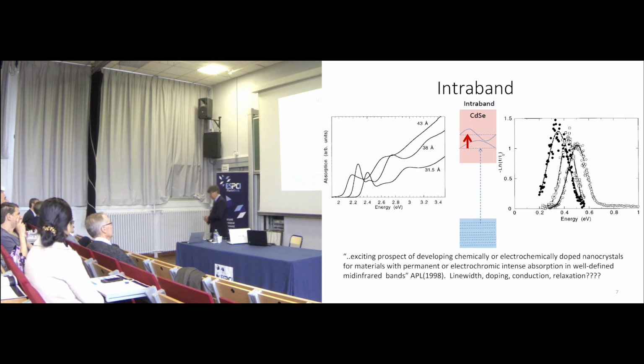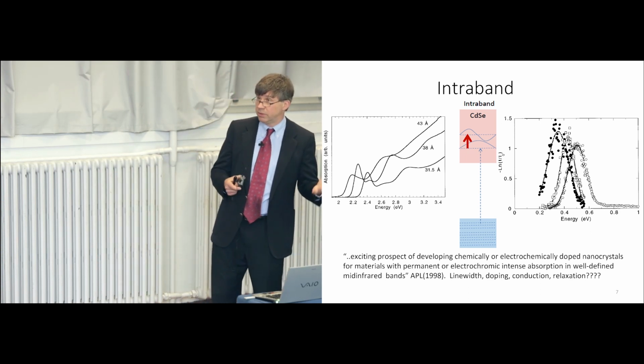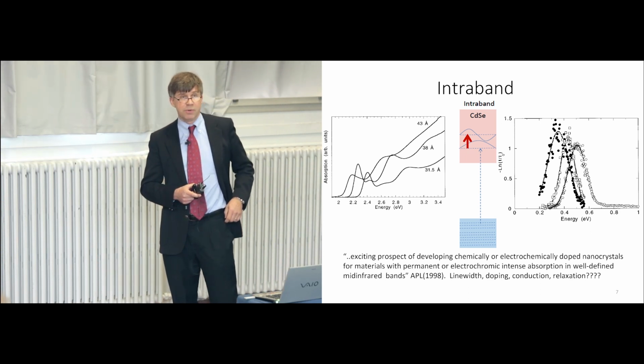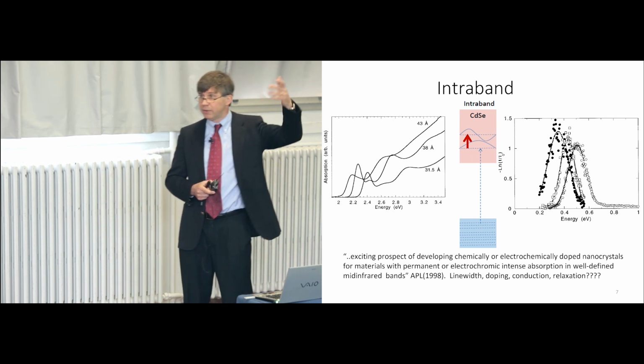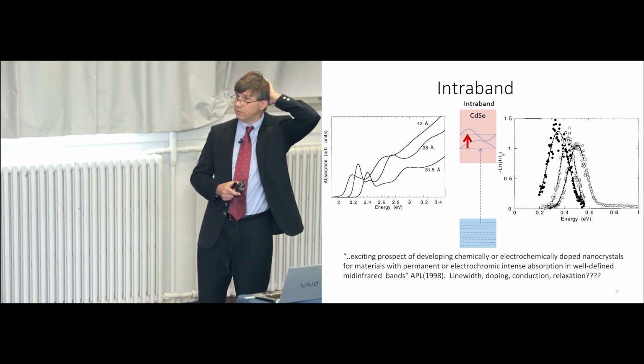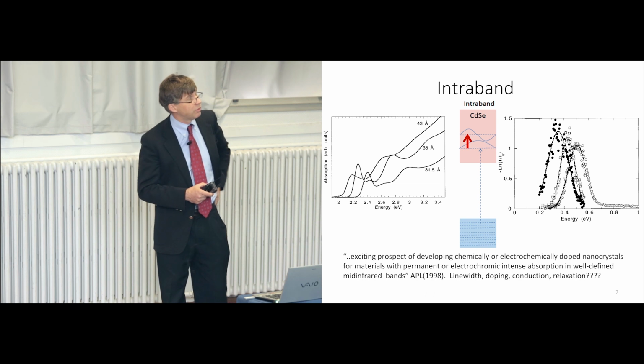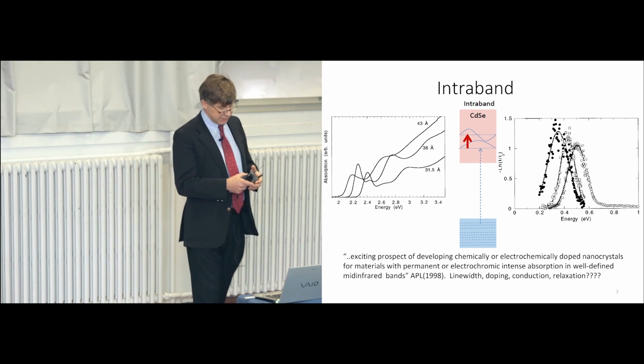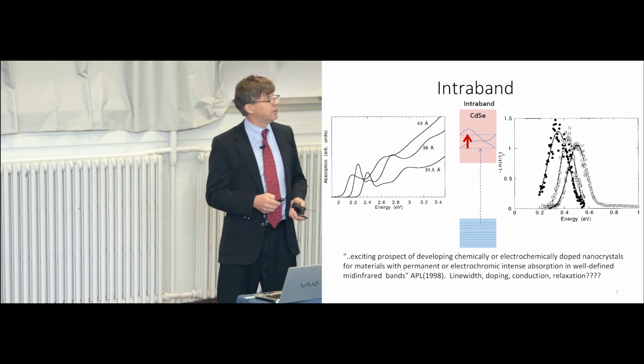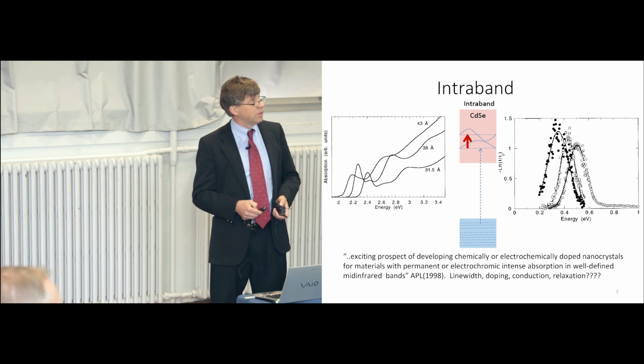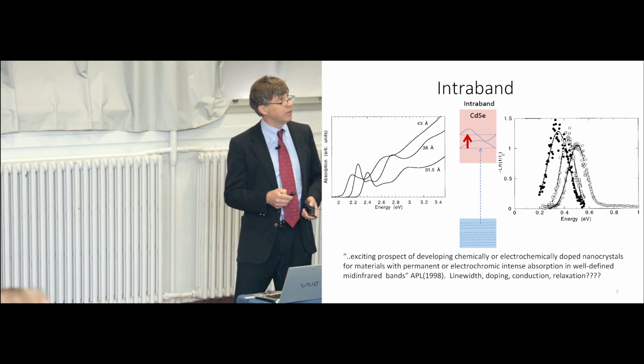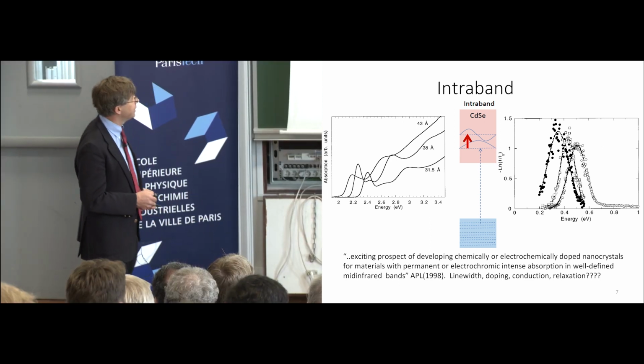So we worked on the core shell for a little bit longer. We worked on two-photon spectroscopy, but it was clear that we needed to do something else. So I was very interested in the broad spectroscopic features of those particles, and I was wondering whether the prediction of those higher excited states was real, what was under those broad bands. And at least one prediction of the electronic structure by Sasha was that there should be a series of nicely high-lying states, especially in the conduction band, that should be well isolated from each other.